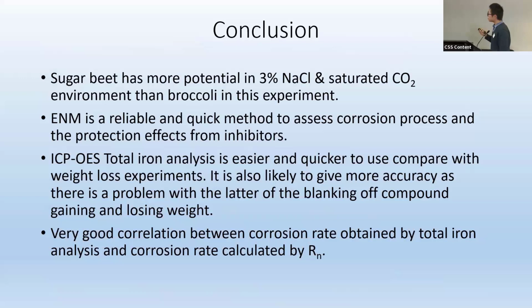So here's the conclusion. The sugar beet has more potential in this work than broccoli. And from the calculated mass loss and the mass loss measured from the ICP analysis, it proved that the electrochemical noise measurement is a reliable and quick method to assess the corrosion process. It also shows the ICP test is an easier and quicker method compared to the traditional weight loss experiment. And there's a good correlation between the results calculated from the noise data and the measured mass loss results.